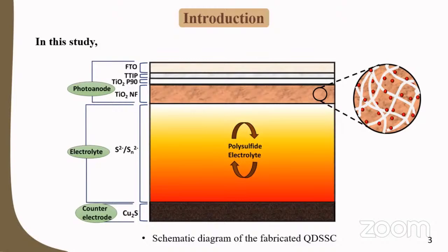In this study, TiO2 photoanode based PbS QDSSCs have been fabricated with polysulfide electrolyte and a copper sulfide counter electrode. In order to enhance the performance of the solar cells by enhanced light absorption through light scattering, photoanodes were modified with a TiO2 nanofiber layer.